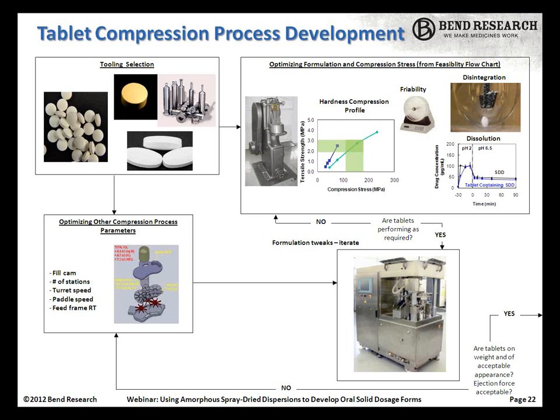But at this point, we're not expecting surprises on dissolution and disintegration because we've really done this at the small scale. But obviously, we do the confirmation, and then we're looking at things like content uniformity and assay become the metrics that we're looking at during the tablet development here. If we do see a surprise at this point in our dissolution or disintegration, more often than not, we'll end up being able to identify that as something to do with a long residence time in a feed frame, a lubrication, or something like that that might require a final tweak.